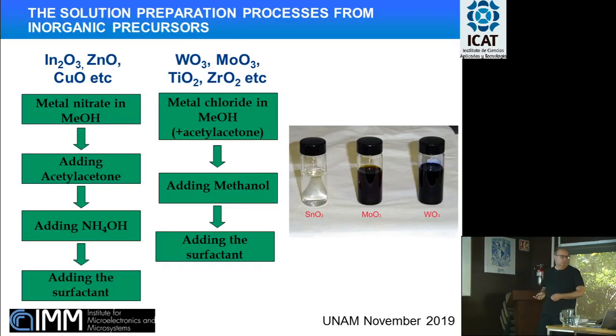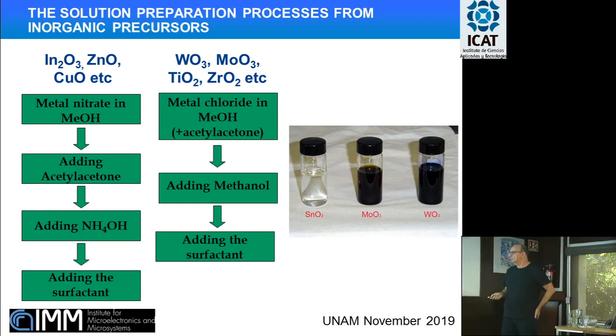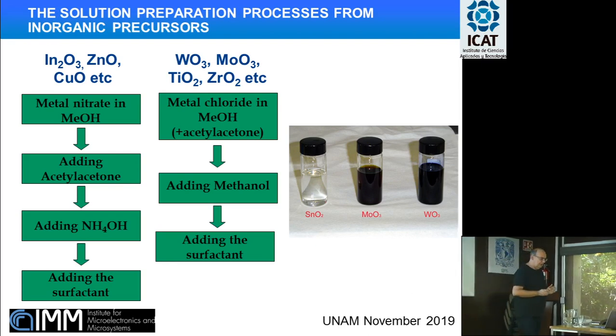And we know how to make these particles. These are exactly the same processes that we have developed for thin films. This is why the first part was important. With the first part, we already know how to process, how to prepare these small particles. In the case of inorganic nitrates, we have the dissolution of our salt in methanol with acetylacetone, with the base, no precipitation. In the case of chloroalkoxide, we just react our metal chlorides with methanol, in some cases plus acetylacetone. We add methanol. We don't have to do anything else. Adding the surfactant is related to the thin film deposition. I forgot to eliminate this part. So, from the first part, we know how to prepare, how to define these small particles.